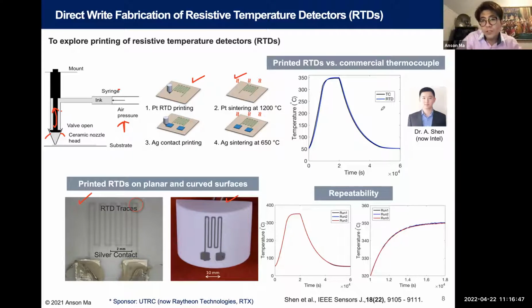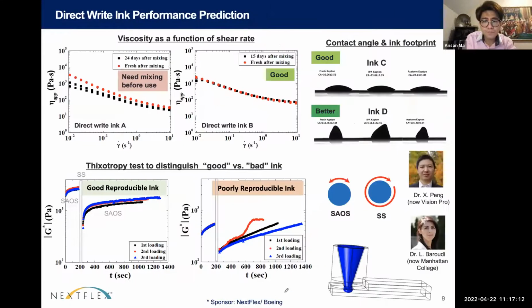But of course, we'll also check the performance of this versus a commercial thermocouple. And you can see that in terms of the temperature response, it's very comparable with the commercial one, except that now you can do it on different conformal surfaces. It doesn't have to be flat. The sensor could be directly on something with a topology. And then we'll also check the repeatability. And this work was published in IEEE.